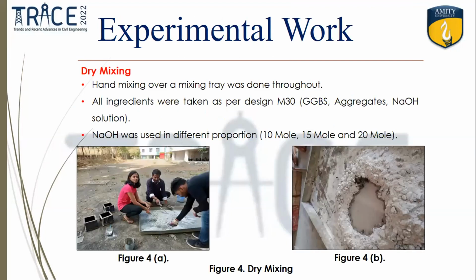My experimental work started with dry mixing of the materials. The materials which I used were GGBS, aggregates, both fine and coarse, and NaOH. NaOH acts as an admixture which increases the hydration process, which GGBS with water alone cannot have. I made 3 different mixes with NaOH. The difference between them was the molarity, the concentration of the solution. I used 10 moles, 15 moles, and 20 moles, as I have read in many literatures that the molarity should be greater than 8, but should not be more than 20 or 25. So I utilized these 3 molarity concentrations.